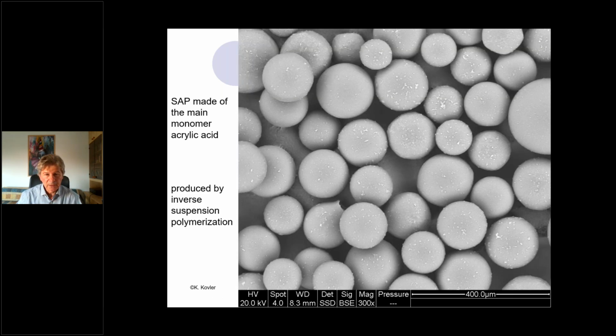And this is, again, returning to the monomer produced by inverse suspension polymerization. Spherical particles. This is before absorbing water. Please look at the particle size. So this is 400 microns. So we have approximately 50, maybe 80 microns. So this is still not nanoscience, but this is a micro world.